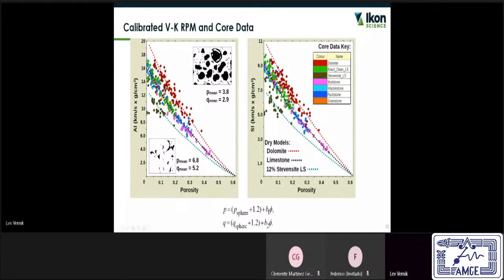So we can see that we pretty nicely match the three entities here: the dolomites, with of course different matrix characteristics, the limestone. Interestingly, limestones with different facies and different textures pretty much plot very tightly in acoustic impedance versus porosity space. And then finally we have outliers, such as very soft Stevensite-rich limestones from pre-salt Brazil. Both acoustic and shear impedance are shown here, and we see a pretty much consistent situation in both.